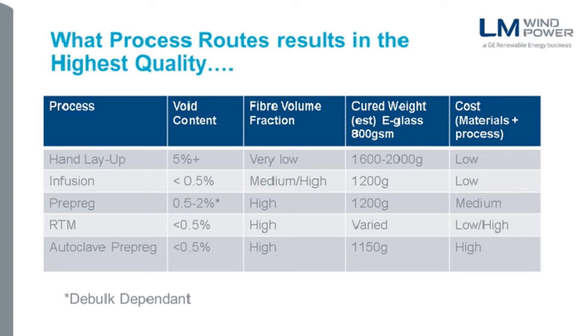Hand layup, again, as we touched on, if you don't mind voids and you're not worried about cured ply weight, because weight equals thickness generally, then actually hand layup is good. Autoclave prepreg looks the best in terms of the numbers I've got here, and that's why Formula One cars, military aircraft, very high specification composites are still built in an autoclave prepreg, because you absolutely get the best quality, but it's high cost, both in processing and materials.